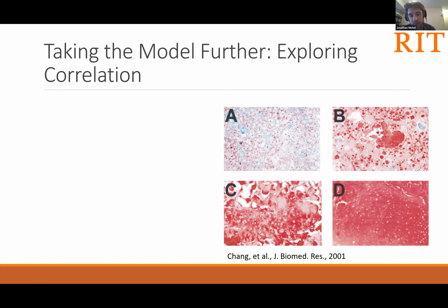encompasses the collagen scaffold. And what you can see is that this structure doesn't grow in a spatially uniform way. Rather, it seems like there are kind of nucleation sites, and the tissue kind of fills in as it grows out from these nucleation sites. And so then our group became interested in understanding what the consequence could be of now having spatially modulated density.